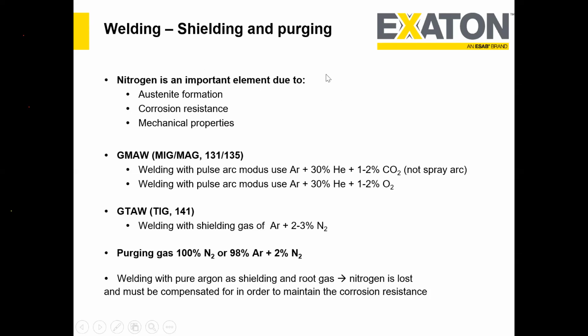So nitrogen is one of the most important alloying elements, and it could also be added to the shielding and purging gases. It is a strong austenite former, it helps to form the austenite. We need nitrogen for that. It gives corrosion resistance, as I told you, it has a strong influence on the pitting resistance. And if nitrogen is reduced by only 1%, the effect on the weld metal comes to around 16%. So it plays a very important role in corrosion resistance and, of course, in the mechanical properties.